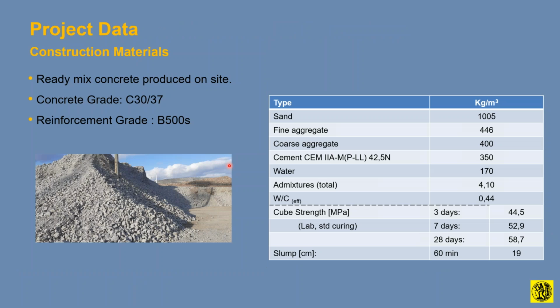The mixed design: the caisson is made of, according to the design specification, a C30 concrete, which is ready mixed on site. There was a batch plant operating on a 24-hour basis because the slip forming needs a continuous supply of concrete, and it's a non-stop operation. So once it starts, it finishes after about 8 to 9 days on a 24-hour cycle. So the entire caisson is constructed non-stop practically.